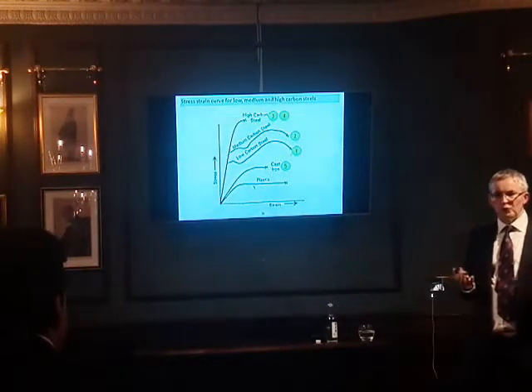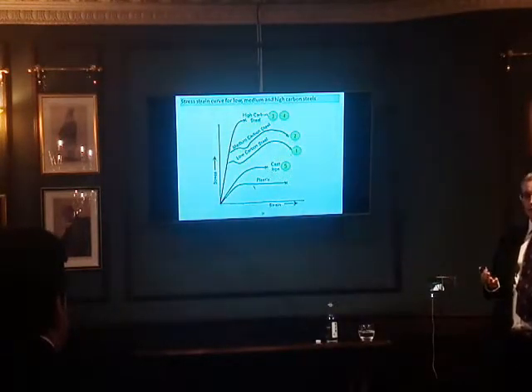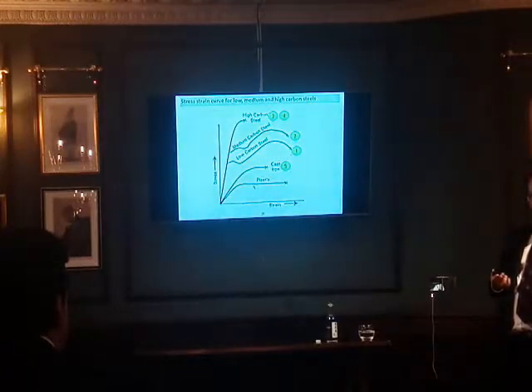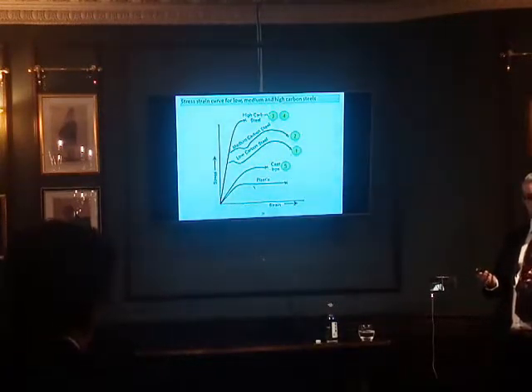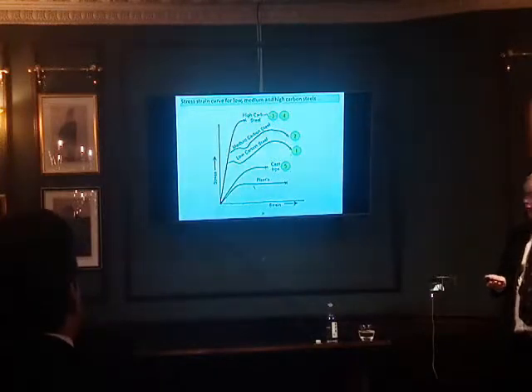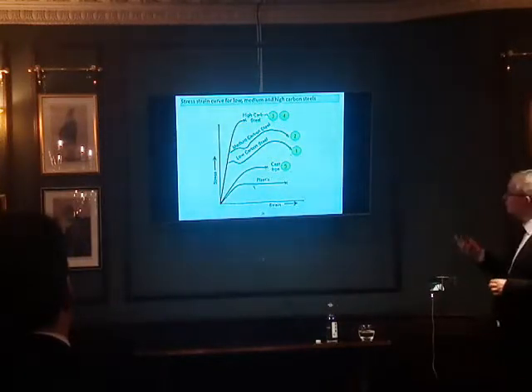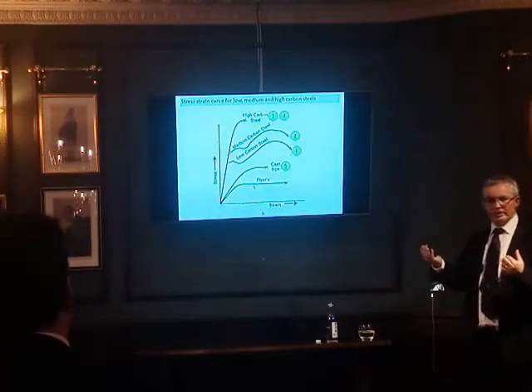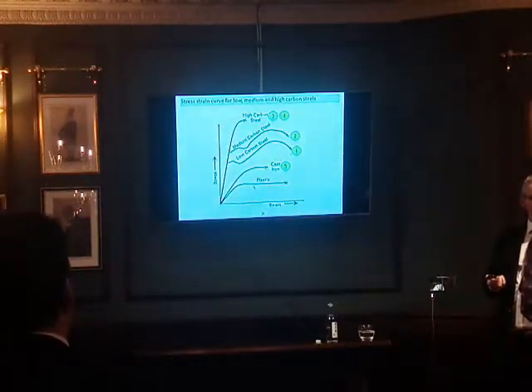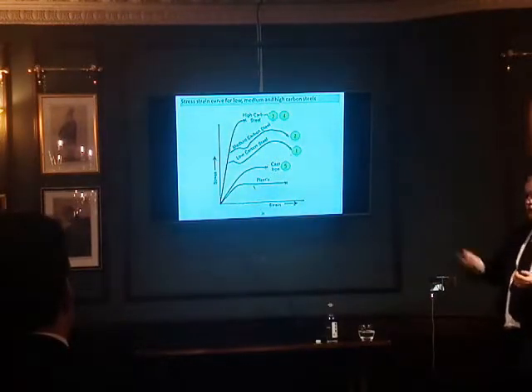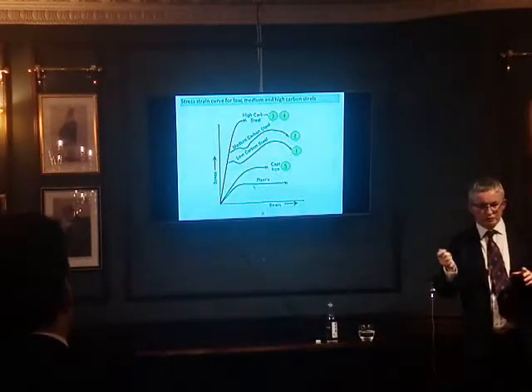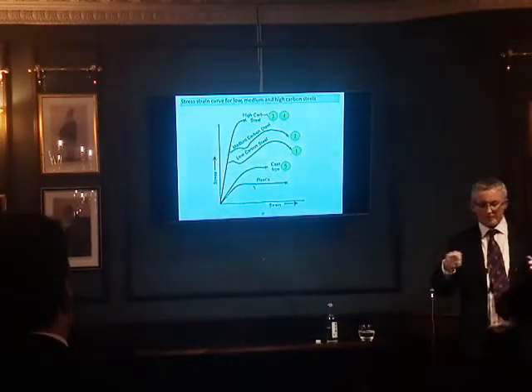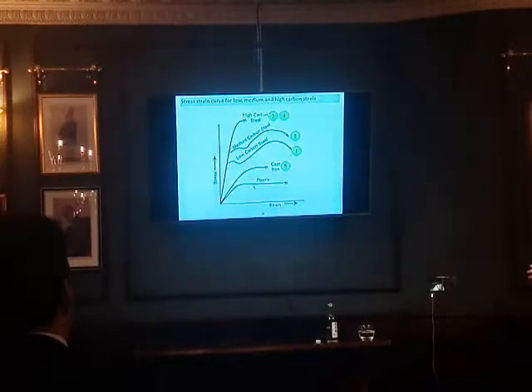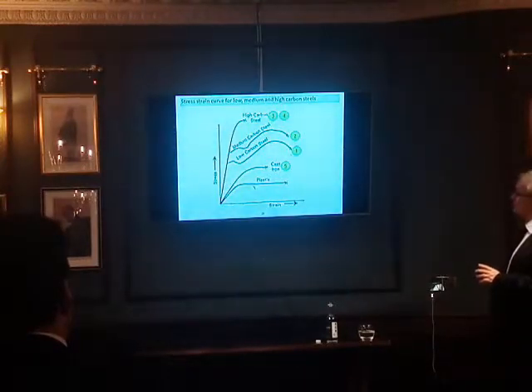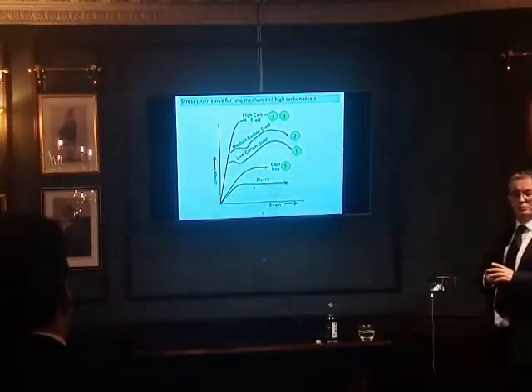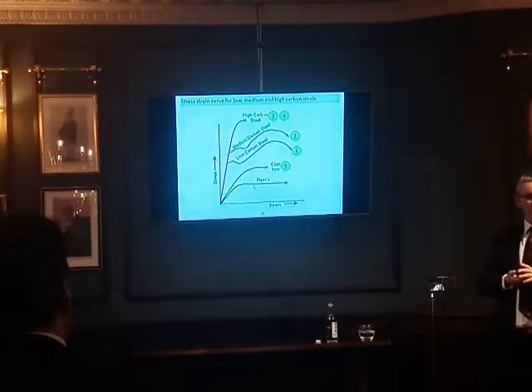So 0.1% carbon or less, with levels of silicon, manganese, sulfur and phosphorus that are at controlled levels. The medium carbon steel is even stronger. Medium carbon steel will go up to about 0.3% carbon. And then a high carbon steel, and that's the cutthroat razor blade of Mr. Bessemer, that probably has something like, that could even be up to maybe 1 or even slightly more than 1% carbon.